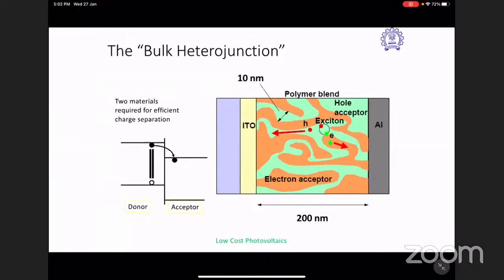So this morphology, the way I have shown, is really slightly more complicated than this one. You have pure domains the way it shows, but there are the domains where this green and orange are intermixed, and those are the regions which are connected to the pure green and pure orange, which basically take away the charges from those mixed domains. And the mixed domains are important for charge generation, and these pure domains are important for the charge transport, and interfaces need to be clean, otherwise you have lots of interfacial losses.